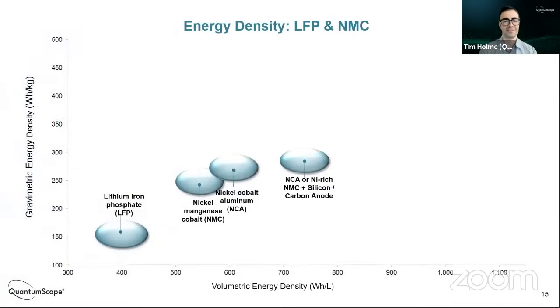So this is another way to see the energy density landscape. On the y-axis is gravimetric energy density, so energy per mass of the cell, and on the x-axis is the volumetric energy per volume of the cell. And lithium iron phosphate is pretty significantly behind some of the nickel-rich chemistries. So that's one of the main reasons why you don't see LFP in long-range electric vehicles in the West today.